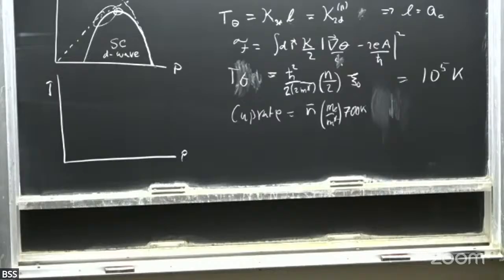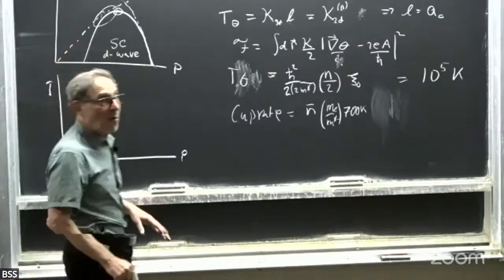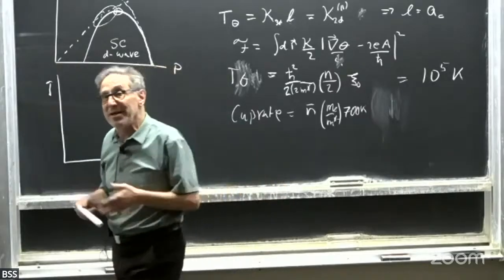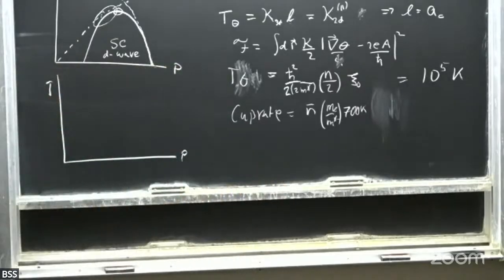And these best data are actually on YBCO, which also turns out to be the least anisotropic, I mean, it only has a resistance anisotropy of 100 or something like that. So it's still rather two-dimensional, but much less. Okay, but I'm glad you caught that. That's an important point. It depends what hat you put on, whether you want to treat these as two-dimensional or three-dimensional.